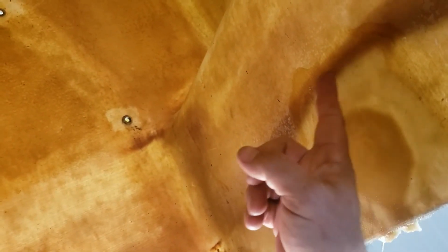Let me flip it over and I'll show you the inside of the tank. Okay. This here is the repair. You see the outline of the hole that was in it. This is approximately, I think, about 10 layers of BID, coarse woven glass with epoxy. And the way that you would properly do this, you take the thickness of the material and you scarf out a taper about a 10-to-1 slope. So this is probably scarfed out, I don't know, maybe 2.5, 3 inches around every one of these repairs. And let me flip the phone over and I'll show you on this bottom one.